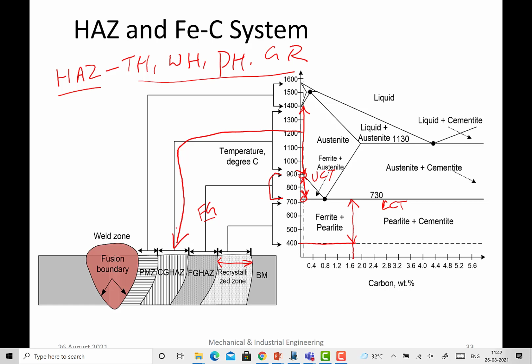So if you expose at 1000, the grains will be a little coarser, maybe say 12 micrometers. If you expose the same at 1300 degrees centigrade, they will be further coarser, say 15, 18, 20 or 25 micrometers. So the grains will get coarsened, and whatever you will be getting here, the coarse grained austenite will be producing the coarse grained pearlite or coarse grained martensite accordingly, okay.